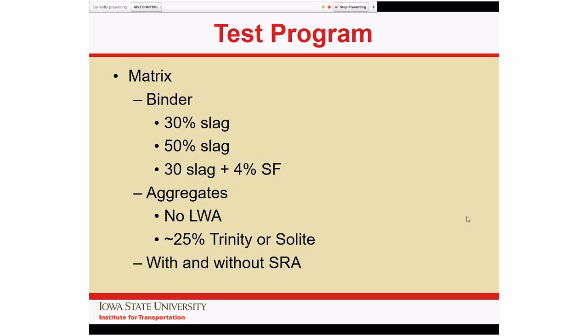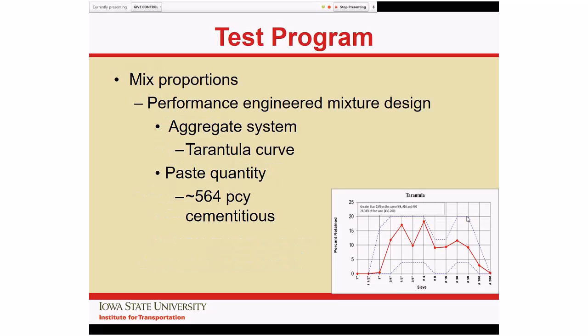So we put together a test matrix where we did 30% slag, which is pretty much your standard approach. I also decided to push the envelope up to 50% slag and see how well it would perform. We also ran with a 30% slag with 4% silica fume. Our aggregate systems were typical aggregate gradations, or substitution with about 25% by mass of either of the lightweight fine aggregate materials. We also ran a couple of mixtures with and without shrinkage reducing admixtures to see what effects they would have.